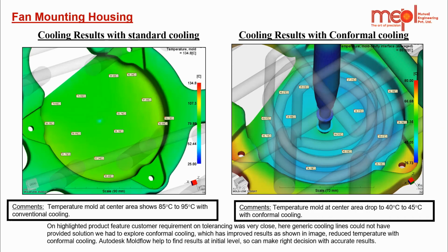To overcome this issue, we explored conformal cooling for such hub areas. After using conformal cooling for this part, we drastically changed the temperature of the part. Not only the temperature, we also could achieve the close tolerance and dimensional stability of the part. This way we could get accurate decisions and accurate results for this part.